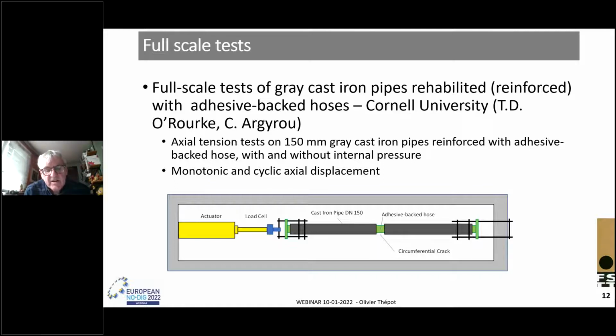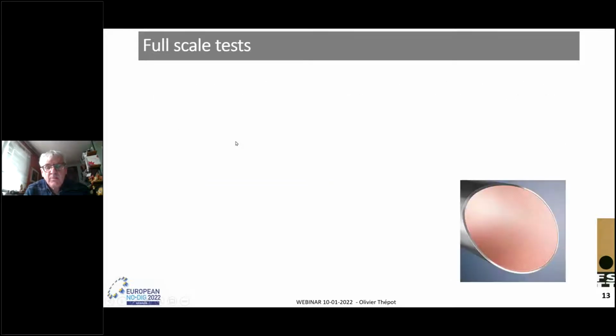The inner liner was continuous and attached at the ends. One end was fixed and the other end was connected to an actuator on the left, which could impose openings of more than 200 millimeters. Strain gauges attached to the pipes made it possible to measure the extension of the liner debonding zone. We will see that this debonding zone is very important. The tests were carried out firstly without internal pressure and then with internal pressure.